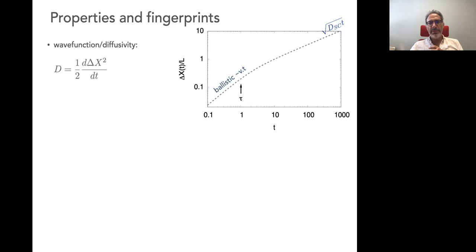So first thing is this mean square displacement, or here what I've drawn is the square root of the mean square displacement. So this is a typical semi-classical behavior that you encounter in good clean silicon. The spread of a wave function when you throw it into material has a first regime that is ballistic, where the spread goes linear with time. And then you hit this typical scattering time, and then in this log scale you change slope, which means that you really enter a diffusive regime where the spread goes like square root of time.